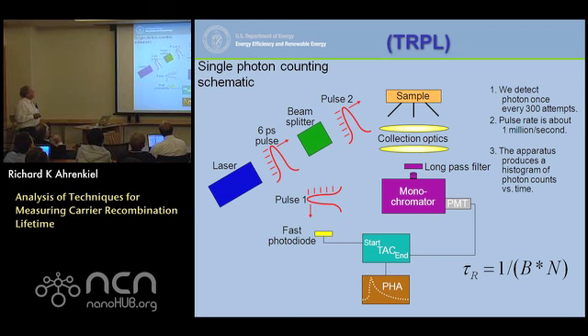Well, this is the basic time-resolved PL, single photon counting, which we adopted in the middle 80s. You have a pulse laser. Here's a sample. A bunch of electron-hole pairs are generated. Photons come out. You collect them with the collection optics, and you focus the light on a monochromator to the band edge, the band-to-band radiation, and now one is able to see single photon events. If we connect a fast oscilloscope here, we'll see these little photon blips actually coming through the electronics.